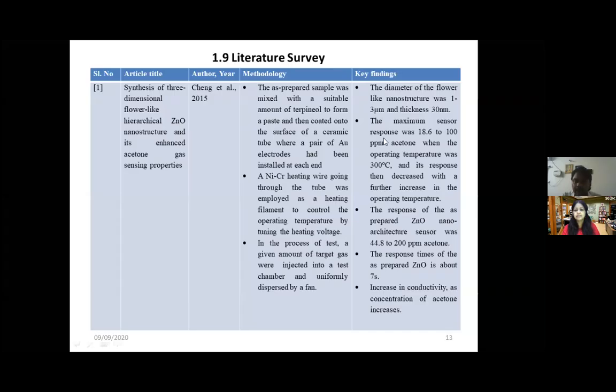So this ZnO metal oxide semiconductor has been operated at 300 degrees Celsius with a response of 18.6 to 100 ppm of acetone. But the exhaled breath concentration range is 1.8 ppm to 20 ppm. This is higher compared to what is in the exhaled breath concentration range. And the response time is 7 seconds, whereas for gas chromatography, it is 45 minutes to 1 hour. So we have reduced that, and this becomes portable. For these advantages, we go for a nanostructured chemiresistive semiconductor material.